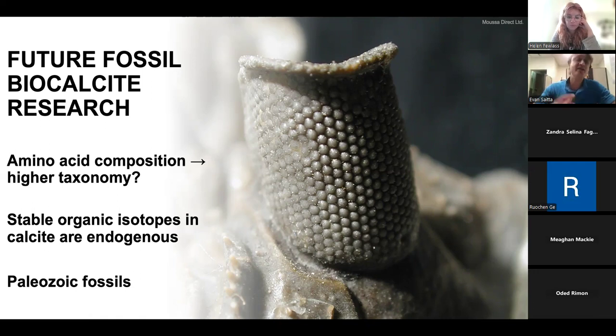You also have the potential of really interesting stable organic isotope studies, where if you know that, say, the amino acids within these calcite crystals are likely to be endogenous and not representative of contamination, then any stable isotope work you do on these samples, you can more confidently ascribe to the specimen or the organism itself rather than some sort of environmental contamination.